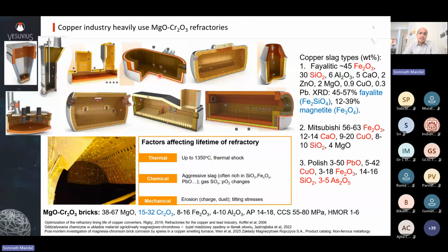So you can see the industry uses a variety of these furnaces. You're going from shaft furnaces, Isasmelt, smelter, copper decanter, Pierce-Smith converter, top blown rotary converter, electric slag cleaning furnace, and then a variety of anode refining furnaces from rotary to stationary to tilting. And in all of these furnaces, one thing is very common, and that is magnesia-chrome refractories are used for lining these. And there are a variety of these refractories, from 15 to 17% chrome content to 32% chrome content, where it is called chrome-mag refractories instead of magnesia-chrome.